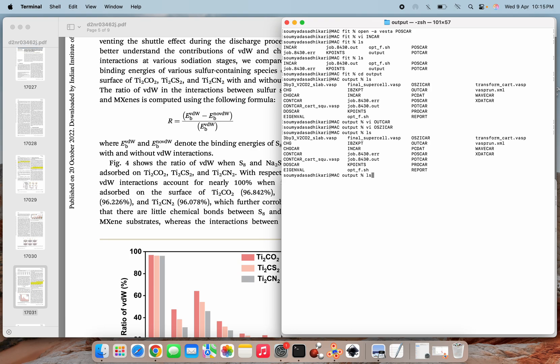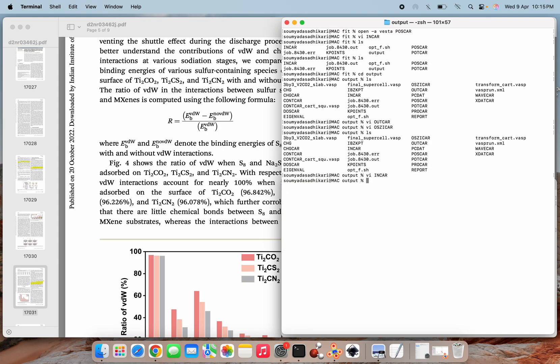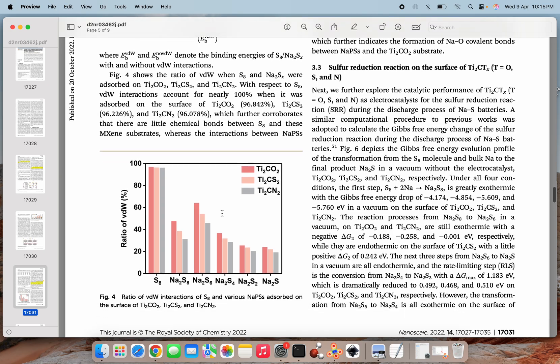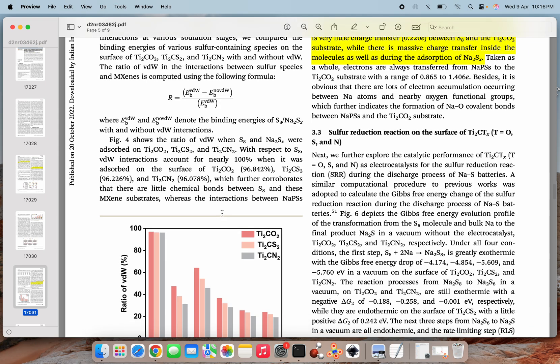If you want to simulate non-Van der Waals species, how you have to go for it? Then you have to simply go and open your INCAR file and come to here and just comment out these two tags. Save the file and with the same POSCAR and K points you can run the simulation. Whatever energy you will get, that energy will correspond to the energy of the non-Van der Waals term. Then if you are already having this Van der Waals energy and you will get this non-Van der Waals energy, then you can find your Van der Waals ratio.